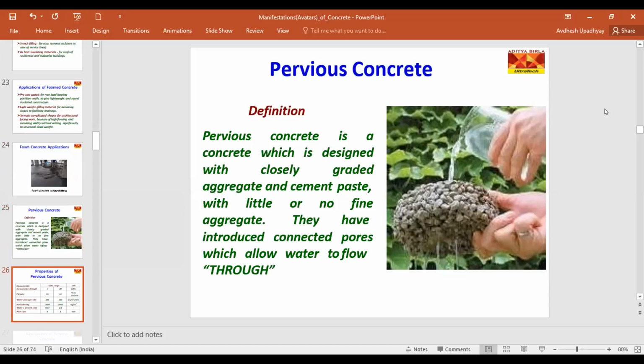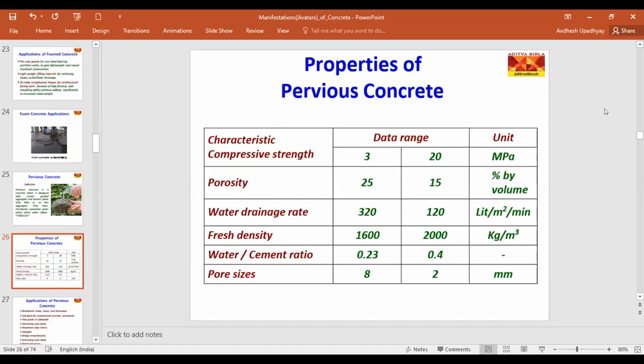These are some properties of pervious concrete. We don't need high compressive strength from pervious concrete. The compressive strength range is 3 to 20 MPa, but we require porosity. So the porosity range is from 15 to 25% by volume. We require a water drainage rate, so it ranges from 120 to 320 liters per meter square per minute. Density is 1600 to 2000, and pore size ranges from 2 to 8 mm.